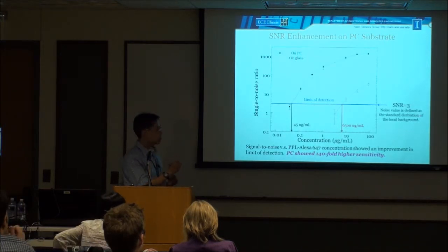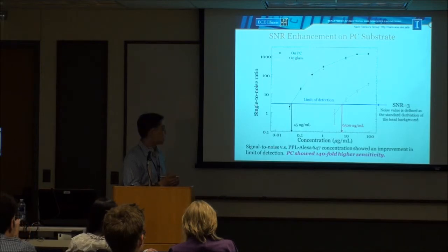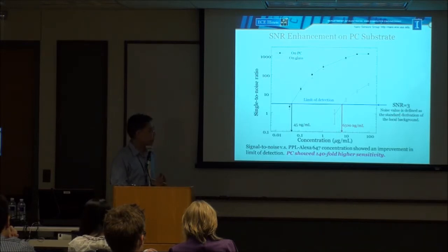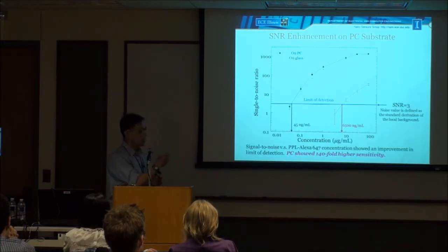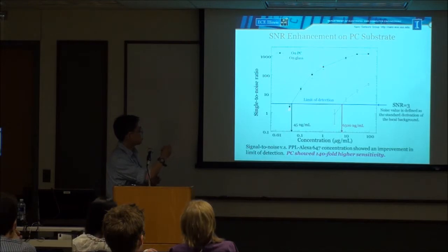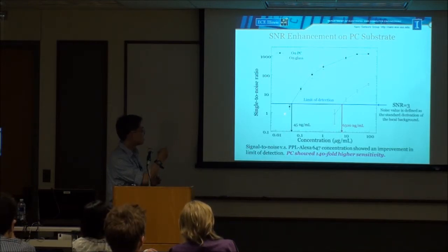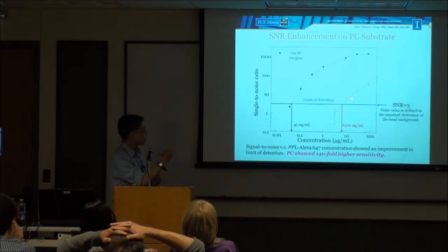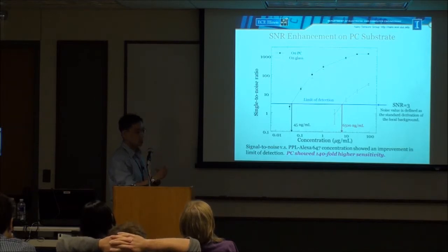So usually people use signal to noise ratio equal to 3 as the limit of detection, which means if you have signal to noise ratio smaller than 3, that molecule cannot be detected. If it's above 3, it's easy to be seen. In this figure, the black curve shows the signal to noise ratio versus concentration measured on photonic crystal substrate. The red curve is measured on glass substrate. It's very clear that for each concentration, the photonic crystal substrate provides a much higher signal to noise ratio.